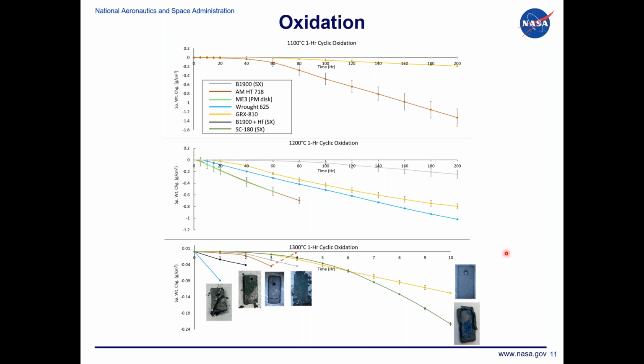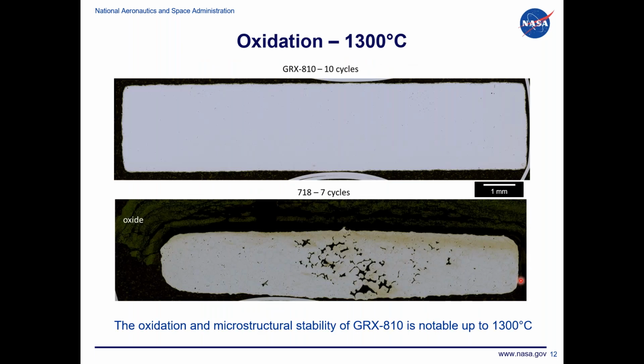All of these alloys are losing weight at a pretty rapid rate each cycle here. But GRX-810 is a much more stable alloy at this temperature, and it performs better than even the alumina formers. It might have to do with the fact that these superalloys are also starting to melt, where GRX-810 isn't. But this is a great comparison, I think, of just how much more stable the GRX-810 microstructure is compared to the more conventional superalloys.